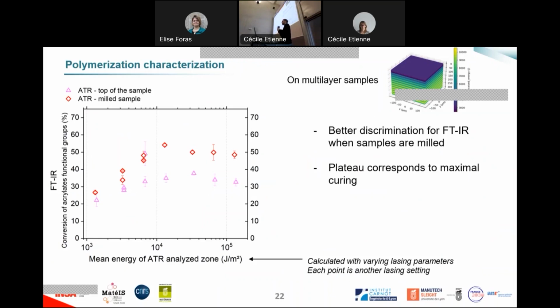So it permits us to locate what are the parameters of polymerization that are sufficient to provide the polymerization we need. But the problem is that we have some inhomogeneity. We have a point which is much higher than what we are supposed to have. And this is because we characterize the top layer. When we characterize the milled samples or the overall sample, you see that the values are higher, and it's because I showed you the figure with the energy discrepancy when you go on top, because you provide less energy.